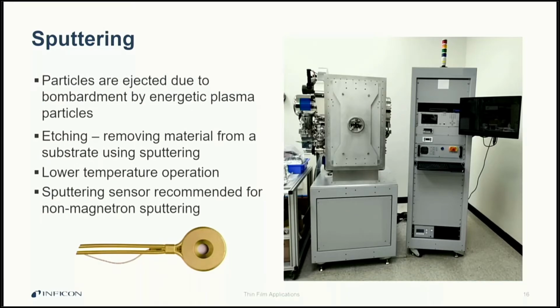Another common PVD application is sputtering. Sputtering is quite different than resistive heating or electron beam evaporation, as it doesn't heat the source material. Instead, a sputtering system bombards what is called a target with energetic ions. These energetic ions are formed by ionizing an inert gas into plasma, and then the plasma will strike the target, ejecting small pieces of the target towards the substrate.